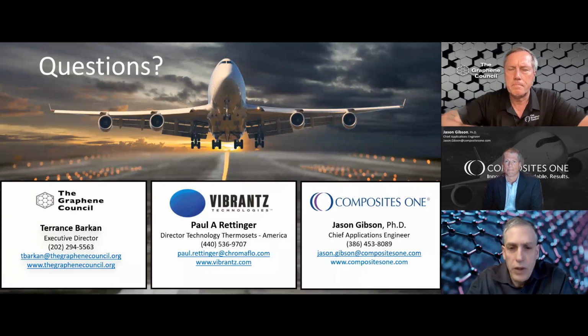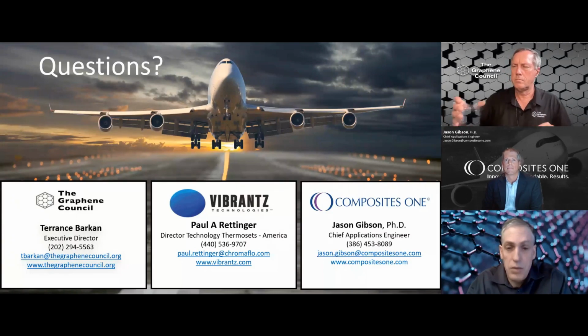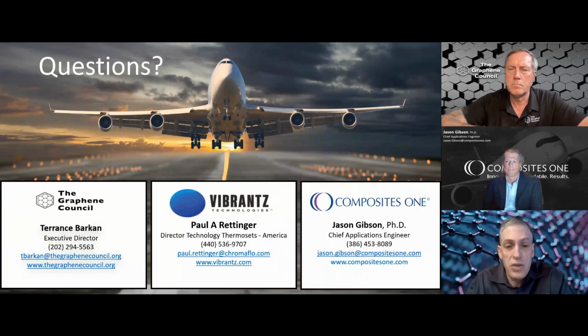Terrence raises a couple of really good points. I hope you don't mind my interjecting here, Terrence. What I notice about this is that just because a graphene didn't perform as expected or hoped in this particular study, doesn't mean that in a different study, a different matrix, different resin, it wouldn't perform very well. Each of these samples that we looked at was unique, and each of them was different. And if you change the test conditions or the test parameters a bit, you could be looking at somewhat different results. We even saw that if you change the loading, it also changed the results. So maybe what was the ideal loading for some samples was not necessarily the ideal loading for others.